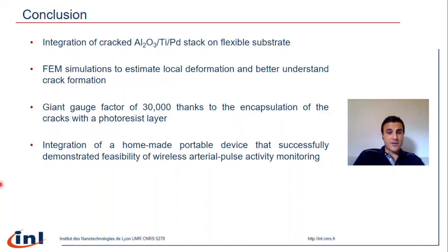We could also get giant gauge factors of 30,000 at 0.2% strain levels by encapsulating the cracks with a photoresist layer. And finally, we could demonstrate the feasibility of wireless arterial pulse activity monitoring by integrating this crack-based sensor in a complete system that communicates with an Android smartphone.